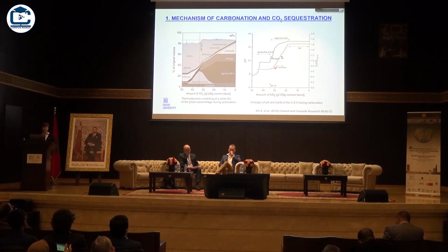Other reactions happen as well. For instance, the monocarbonate will be transformed into stratlingite, which will later also become unstable. Ettringite will become unstable as well. And then finally, the decalcified CSH, when the pH is going down to a level of about 10, will further be transformed into silica gel and calcite, which will, of course, have also an effect on the properties of the material. So you will have a related very big drop in pH and a drop in calcium-silicon ratio of the CSH.